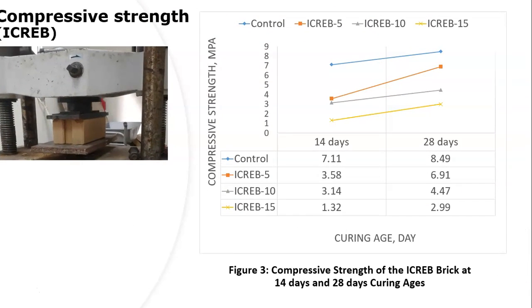Okay, next is the compressive strength result of the ICREB, which is shown in figure 3. Based on this figure, it can be stated that all brick samples of different percentages are showing a decrease in strength as the amount of rubber used was increased. Only ICREB 5 was able to achieve the minimum strength as stated by the BS 3921 with 6.91 MPa at